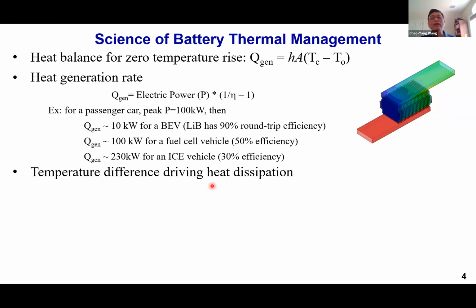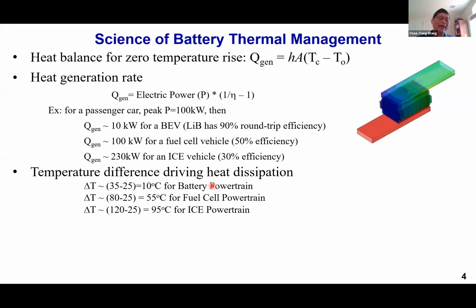The second term is the temperature difference, delta T, that is driving heat dissipation from the cell. Again, if you look at the three cases, for the battery powertrain, we are usually talking about 35 degrees Celsius cell temperature dissipating heat into 25 coolant temperature. So you talk about a delta T of 10. On the other hand, for the fuel cell powertrain, which operates at 80 degrees Celsius, you have a 55 temperature difference, and 95 for ICE, whereas the coolant for ICE typically runs at 120 degrees Celsius. So the temperature difference is tiny also for the battery powertrain.